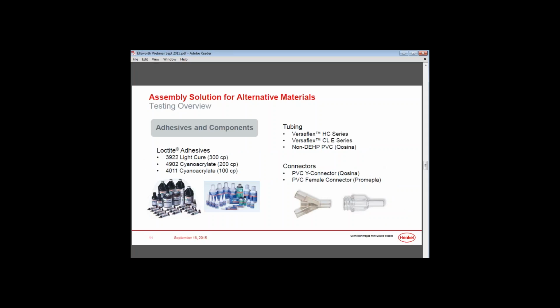The components that we used, as Tom mentioned, two of the VersaFlex HC and CLE series materials. We also sourced from Qosina a non-DEHP PVC to include in the testing. The connectors were both PVC materials, one a Y connector where the tubing is inserted into the ID, and then one female connector where we use the same tubing to insert onto the OD of the connector.